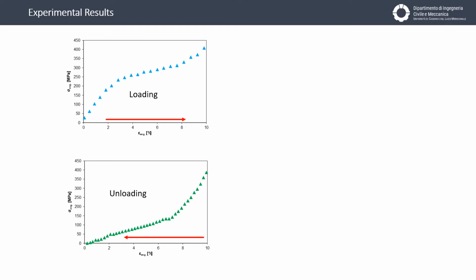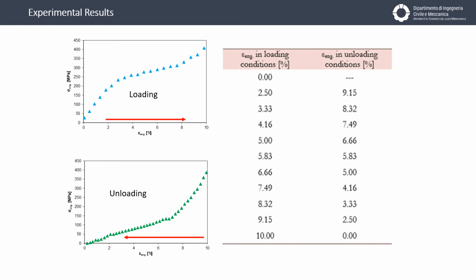In order to analyze the position of atoms in the microstructure, we have to perform X-ray diffraction on the specimen, and we use the tools described in the previous slides, using a step-by-step technique. The steps investigated were in the loading condition, then the unloading condition. We have used different steps, 2.5% of engineering deformation and so on, up to 10% of engineering deformation. And then in the back direction, we used loading steps in order to perform the diffraction on the calibrated length under load.